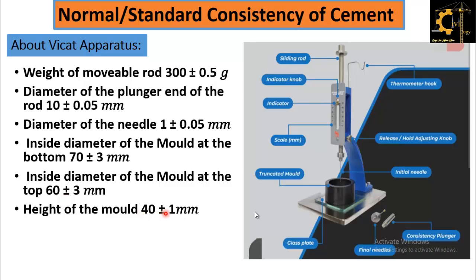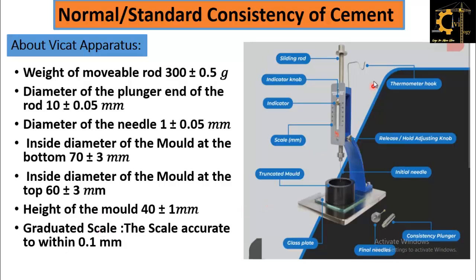And the height of the mold, as you can see, the one in the black color is the mold which has to be filled with the cement paste, and its height is 40 plus minus 1 millimeters. And this is the graduated scale, accurate to within 0.1 millimeters, with a total of about 50 millimeter graduation.